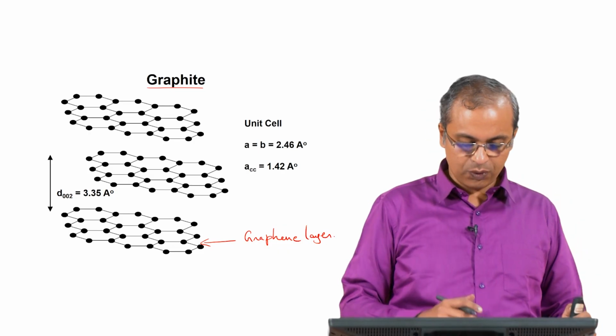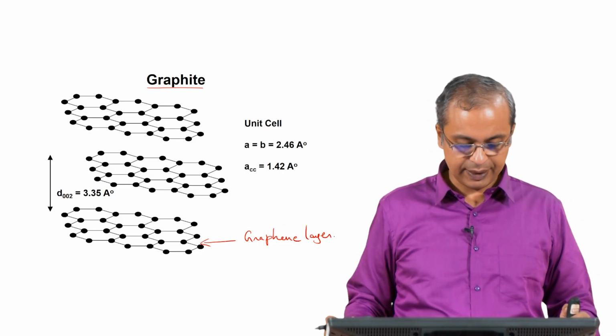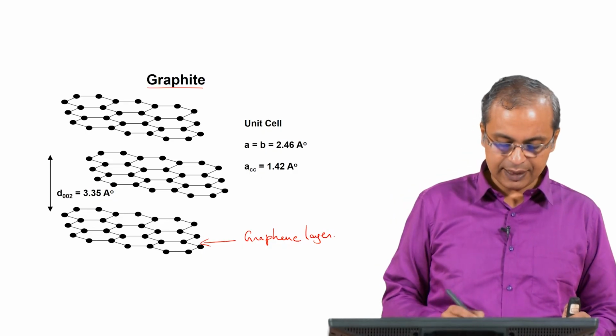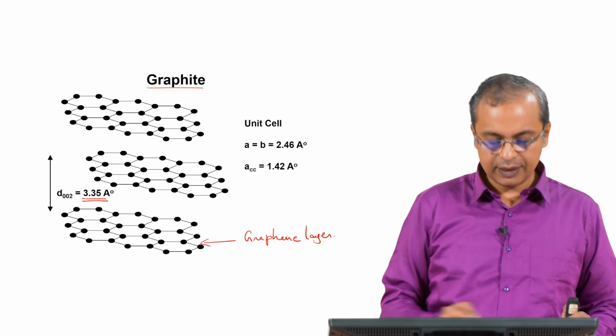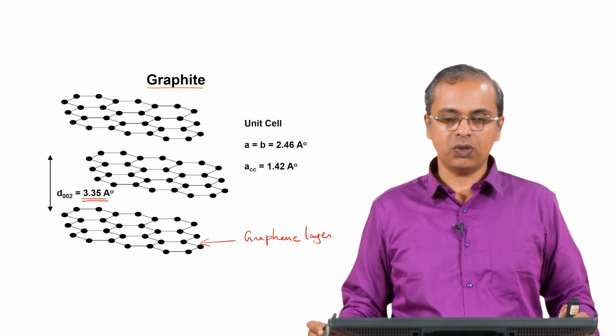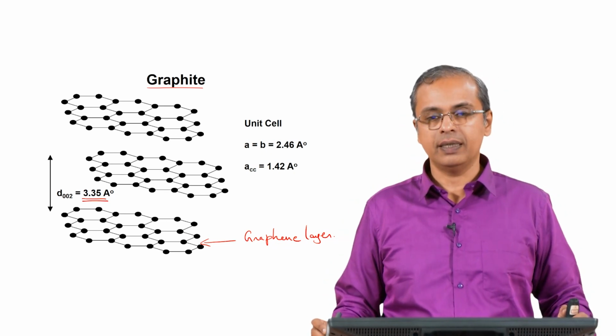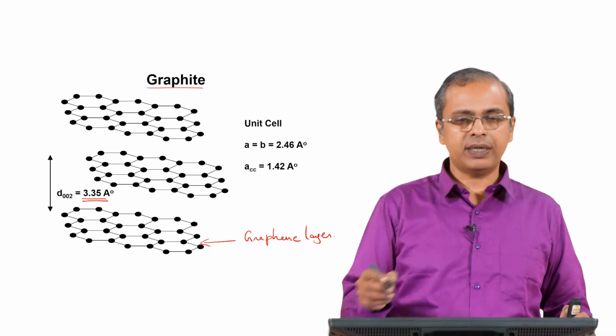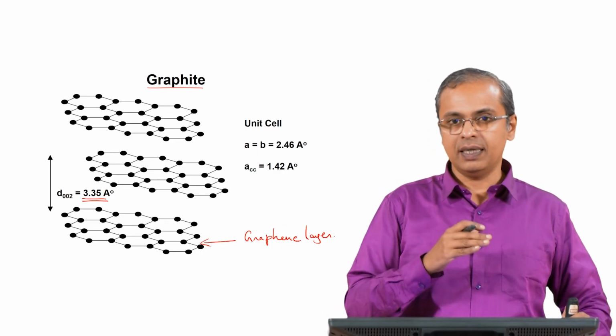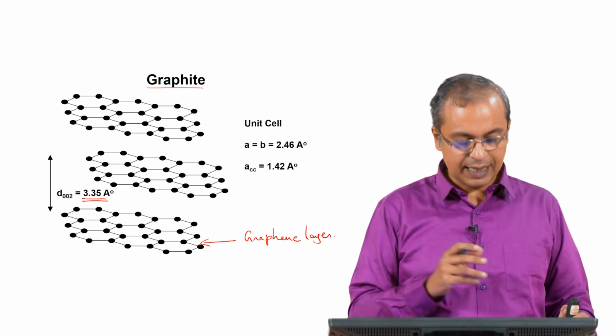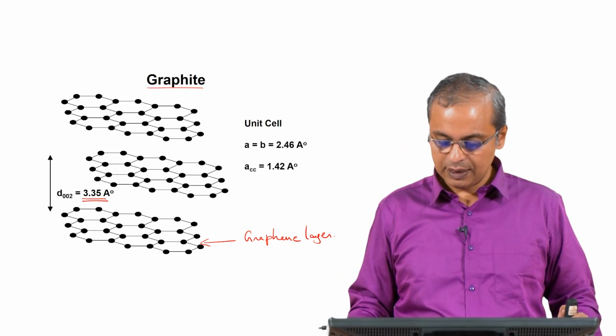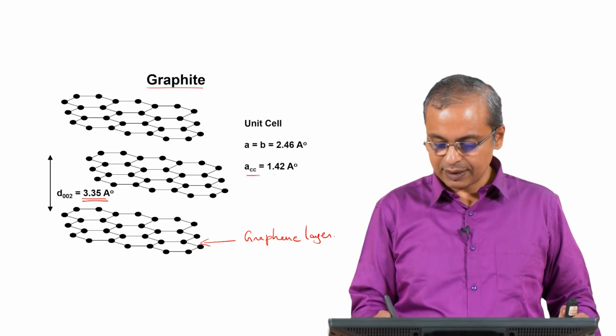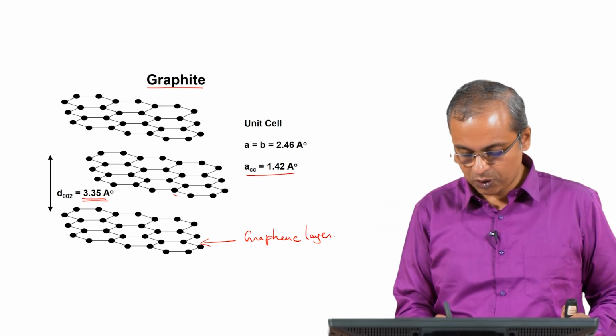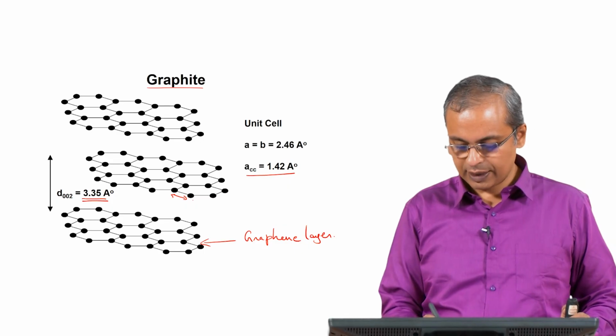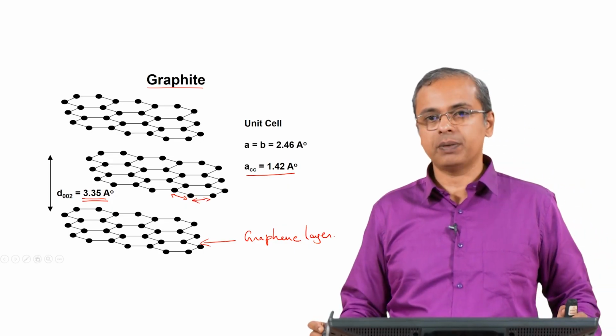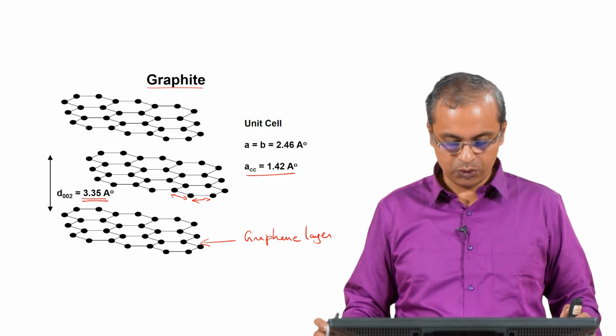Each layer is referred to as a graphene layer. And you have a layered structure where this is how the layering is done, and the spacing between those layers is 3.35 angstroms. This is the D002 planes, called 002 planes if you know the crystal structure notation, but if you do not know, it does not matter. You just have to remember that it is a layered structure, layers of carbon atoms are present, and the spacing between them is 3.35 angstroms. The carbon-carbon bond length is 1.42 angstroms. So, that is basically this bond length here or this bond length here, about 1.42 angstroms.